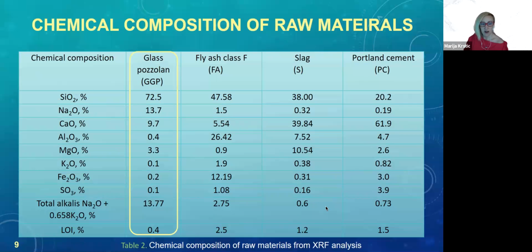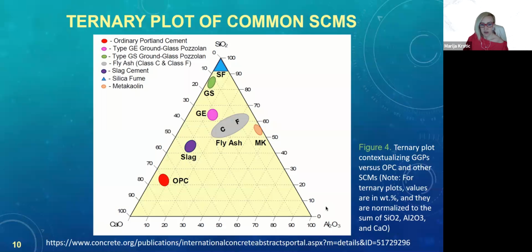By using XRF analysis, we found that GGP contains more than 70% of silicon dioxide, which is significantly higher than other raw materials used in this study. LOI was determined from TGA analysis, and it was only 0.4, way lower than for other materials. The ternary plot just shows where GGP stands in terms of silicon dioxide, calcium oxide, and alumina content. And in this study, we used GGP, ground glass pozzolan, which is soda lime glass.